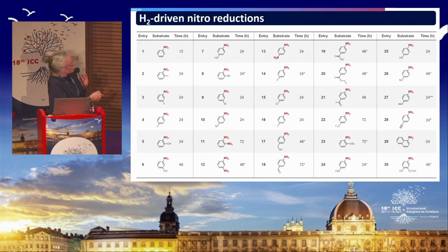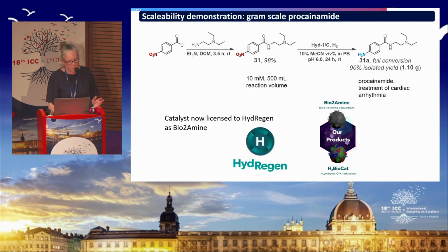We've done this on dinitro compounds and been able to reduce both of those nitro groups, and we've done this on halogenated compounds where palladium will often dehalogenate, but in this case we have full retention of the halide substituent there. And we've done a slightly scaled up, gram scale synthesis to show that you can make a pharmaceutical molecule using this on a scalable quantity. And this catalyst system is now licensed to the spin-out company HydRegen and is now being commercialized for application in